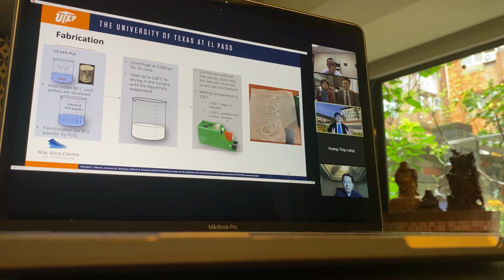So this is the FDM printing method to fabricate our piezoelectric composite. To begin, we dissolve the PLA powder into DMA solution. After the PLA has fully dissolved, we blend the solution with a functional piezoelectric powder to give us the raw material we would like to print. After uniformly blending, we remove the liquid by placing the mixture into a furnace until it's fully dried out, and then we cast the FDM filament through the extruder.